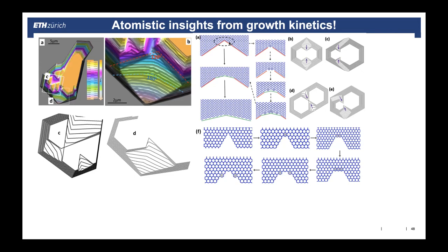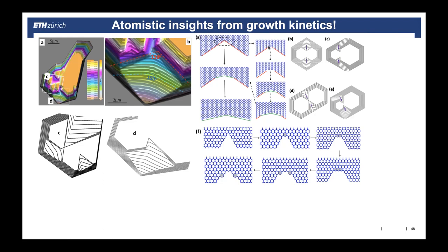But if you attach carbon right in here, in this hexagon, it's very easy. Energetically, it's the best place to put a carbon atom. When you put a carbon atom right into this corner, you have on the left and the right side, again, a nice place to put a carbon atom. So you put the next two things here.